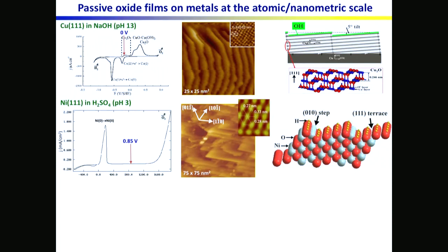So in the 1-1-1 direction, it alternates planes that consist of only anions, and the next one is only cations. And this is completely unstable. This is called a highly polar oxide, and normally these surfaces do not appear. And we did the same experiment of oxidizing the same nickel in very high purity oxygen in the gas phase, and we never found this